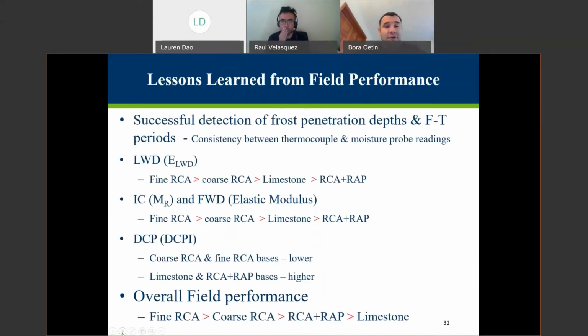And what did we learn from field performance? I think the sensor installation and prediction of frost penetration depths and freeze thaw periods were very successful. Based on the construction data, LWD, lightweight deflectometer, elastic modulus data, and intelligent compaction data, and also FWD data that we didn't mention here, fine RCA right after construction had high stiffness values, elastic modulus and resilient modulus values. And coarse RCA was the second performer. Limestone and RCA+RAP are very similar to each other.